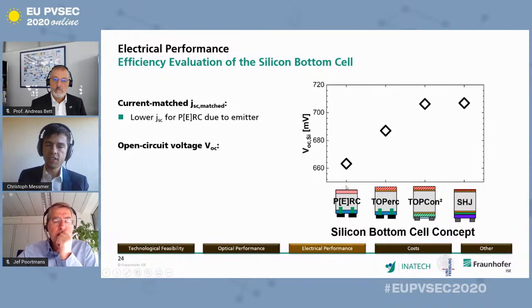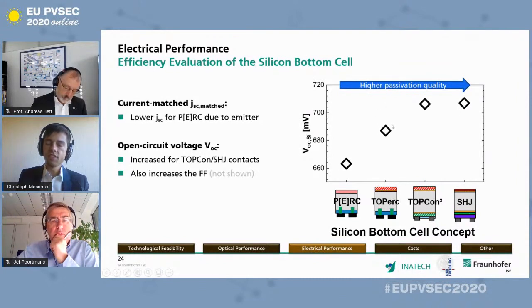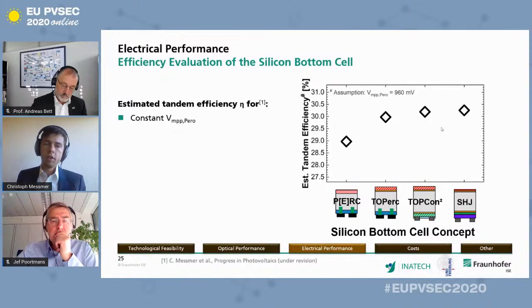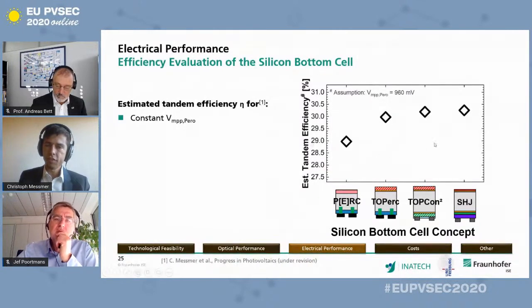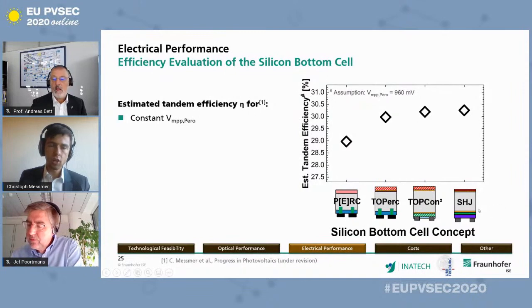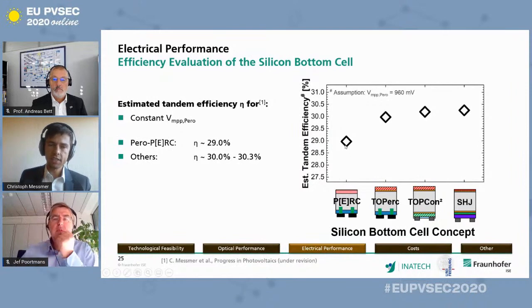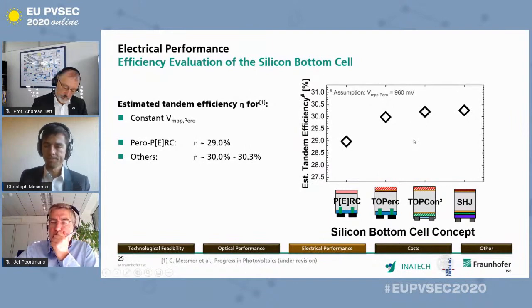For the open circuit voltage, you can see that moving from the left to the right, the passivating contacts increase the VOC due to higher passivation quality, which also increases the fill factor, which is not shown here. Thirdly, we could then go on and estimate a tandem efficiency by assuming a constant VMPP for the perovskite top cell. And with this, we ended up with the tandem efficiencies shown here for each bottom cell concept, for which the PERC concept yielded 29% in efficiency, and the other concepts yielded around 30 to 30.3%.